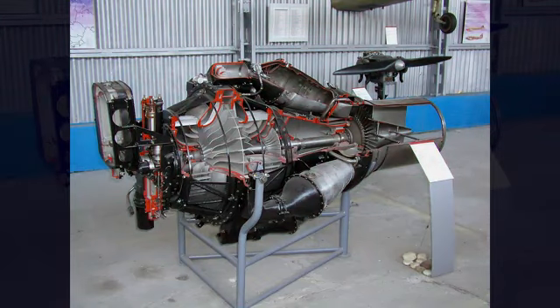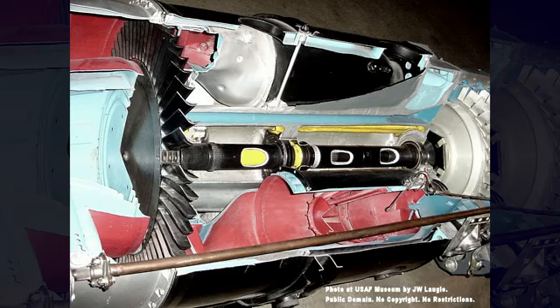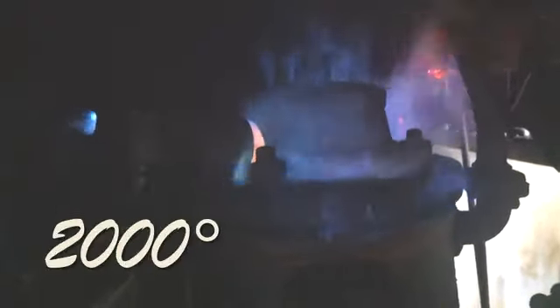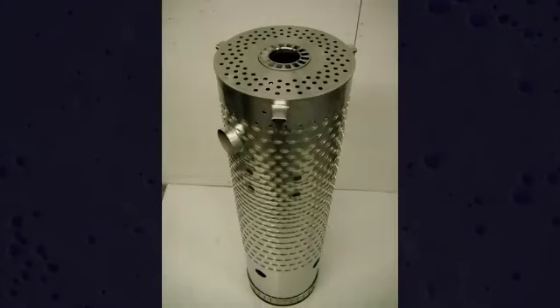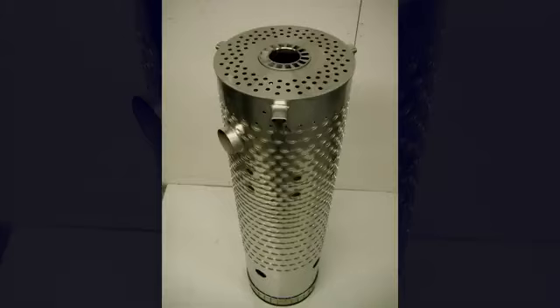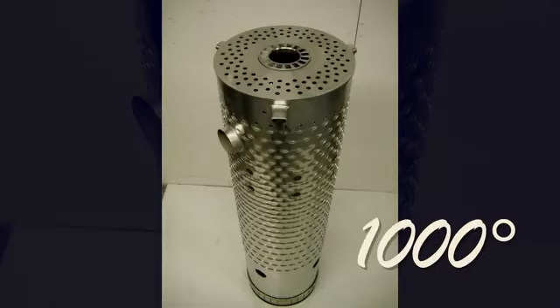With the compressor complete, the combustion chamber, called the combustor, is installed. This is where fuel mixes with compressed air and burns continuously at around 2000 degrees Celsius. The combustor liner is perforated with hundreds of tiny holes arranged in deliberate patterns. Cool compressor air bleeds through them to form an insulating film along the inner walls, keeping the metal temperature around 1,000 degrees lower than the flame it contains.